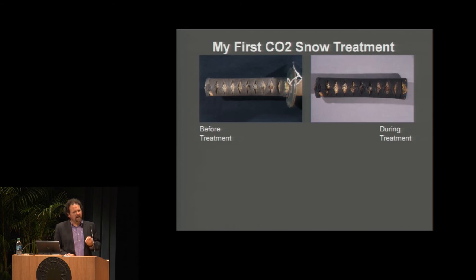And this is actually after I've already vacuumed and brush cleaned the piece. There's still particulate material down between the silk wrapping. How am I going to get that out? The silk has the potential to be damaged. You can see that there were already broken threads. I wrapped it, masked the silk, and was able to go after it with the CO2.